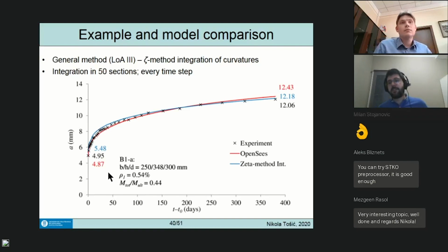Now, this is something that, even in experimental results, is maybe not so clear. It's maybe even bigger, the creep in tension, but it's something the model takes equal to the creep in compression. Basically, the agreement is good, the result is very good considering the experiment. Again, taking into account that if it were a statically indeterminate structure, if I had any changes in reinforcement, all of this calculation would have to be 2, 3, 10-fold more.